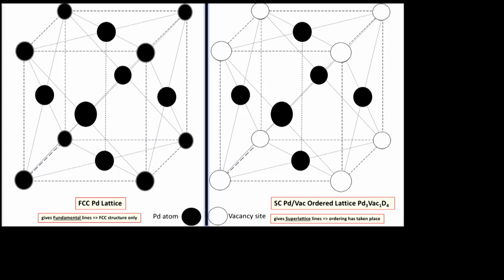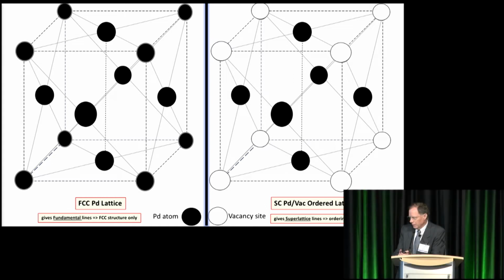The superabundant vacancy form is an ordered lattice of the Pd3 vacancy 1 D4 composition. It's a compound that has that stoichiometric distribution. And what we're really talking about here is that all the corner atoms are missing in this face-centered cubic palladium cell. So that's 1 out of every 4 atoms in this unit cell are gone.